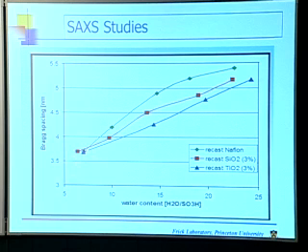We're looking at essentially a crystallinity associated with the water pools in the material. And once water is there, you see a very different spacing for the crystallinity of this material. That is, the water pools are larger and closer together when I have the metal oxide around. And one would argue, based on the other piece of data, that if, as I raise the temperature, I'm going